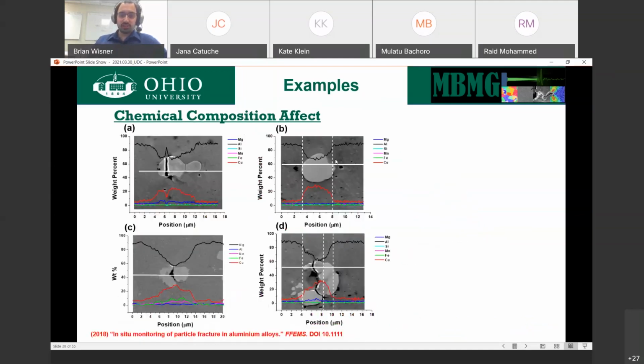Two, if we look into this, we want to keep in mind that not only do we have voids that are different, but we have different particles that exist within here. And as we process this, as we apply loads to this, and anytime you think about processing, there's going to be loads applied, mechanical or thermal. Either way, it leads to stress concentrations, strain concentrations, and damage if we're not careful. This is an example of some of the particles that exist, 3 of which broke, 1 didn't. The copper-rich particles seem to be stronger. That's useful information.